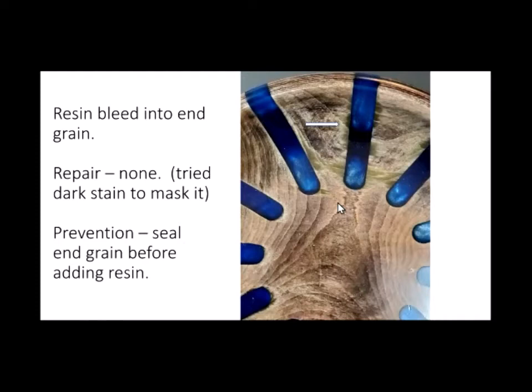And the whole thing turned out very ugly. So this is in the reject pile, but there's a real danger when you do stuff like this. If you're dealing with end grain, that resin will bleed, whether you use pressure or not, into the end grain. On this particular bowl, where you have some of the side grain, you don't see that same effect, but wherever there was end grain, it just went right into it. And it was so blotchy, particularly before I stained that maple.